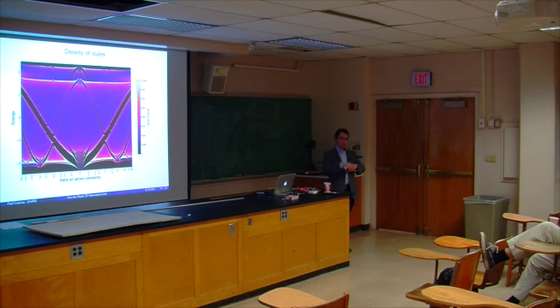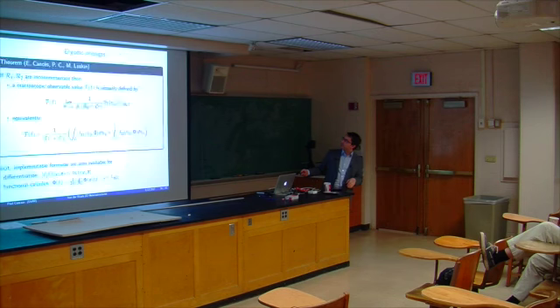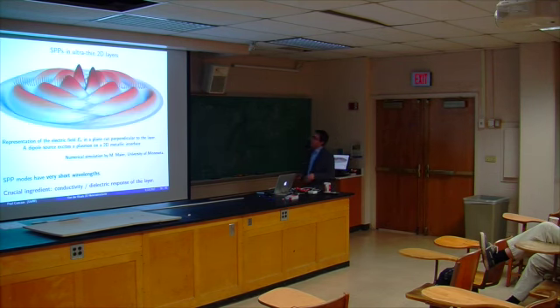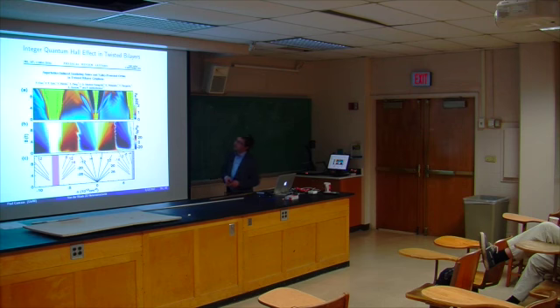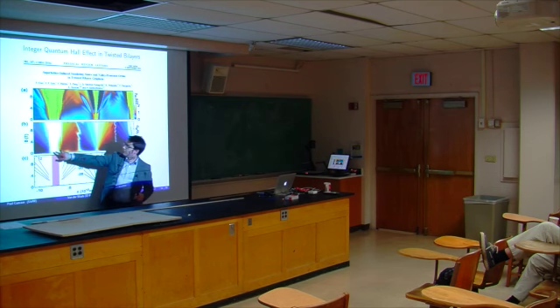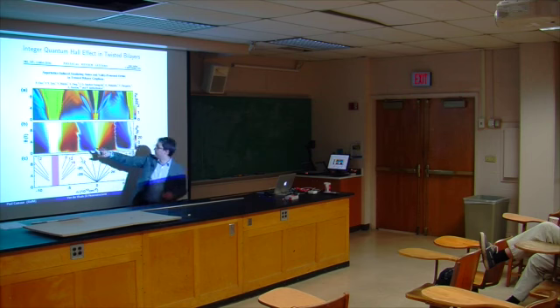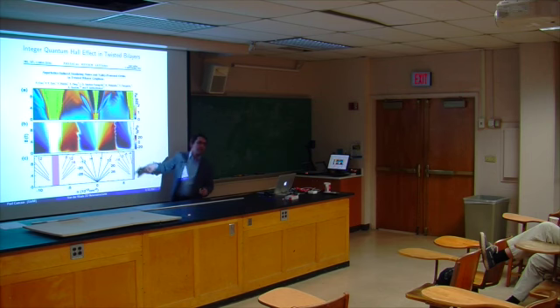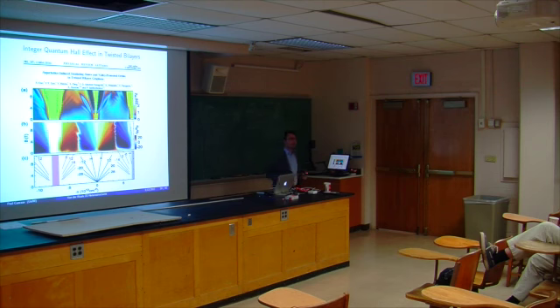two layers, for example, in particular with a very small twist angle. So this ratio of lattice constants plays here the same role as the twist angle, and we could expect similar behavior, as we saw in the picture I had earlier of the magnetoresistance in these slightly twisted bilayers. Over here, it is the same idea that we have insulating states, so gaps appearing because of the superlattice. So this behavior is general and actually happens in graphene.